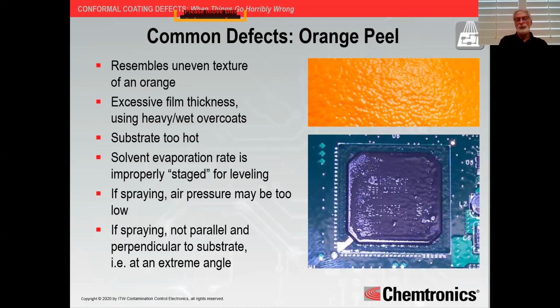If you're spraying, especially with spray guns, again, pressure too low can cause this. Also, if you're spraying, on this last point here, your passes across that board must be parallel to each other and at the same distance with a slight overlap. And they have to be perfectly perpendicular to the substrate. If you're spraying at an extreme angle, you're putting pressure behind that coating, and again, it can push that coating away from that point of contact on your previous coat, and it can result in orange peel. It can also result in other conditions for potential defects.